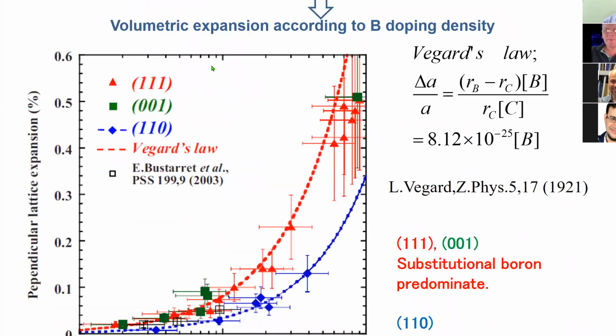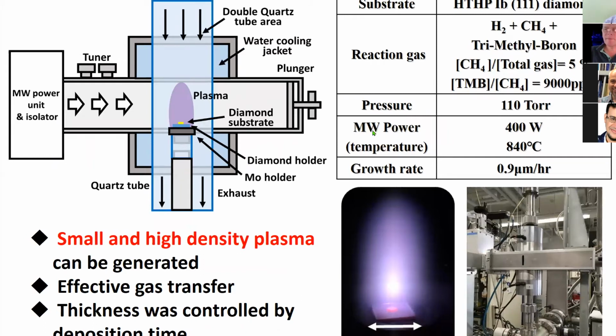The microwave we're using is not continuous. Later, after my conclusions, I'll put some figures to explain our plasma is a little bit different because the microwave generator we use is in pulse mode. A very classical microwave generator has a pulse because we are using magnetrons, and magnetrons show the microwave oscillation start, but it is at high voltage. So there are high voltage and low voltage regions, at a frequency like 50 hertz or 100 hertz.